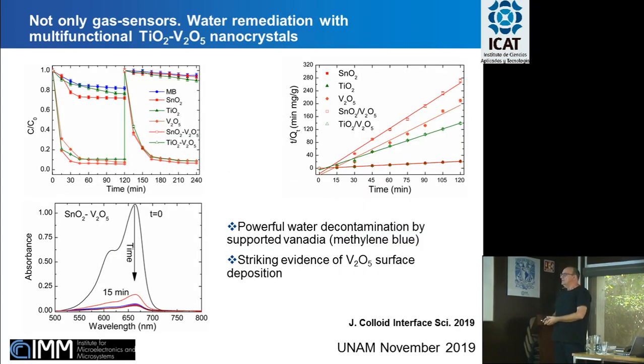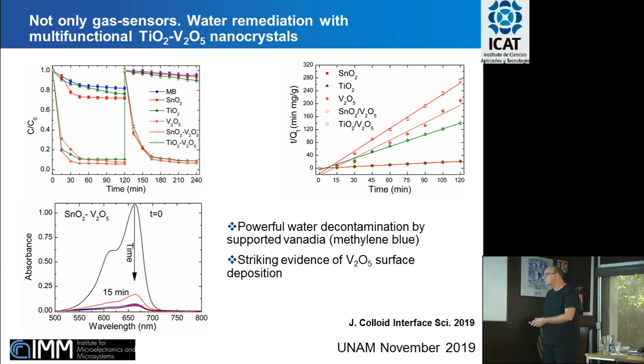And some results about water remediation with these multifunctional titanium oxide vanadium oxide nanocrystals and tin oxide vanadium oxide nanocrystals. We can also prepare other compositions, of course. And we can easily see that there is a powerful water decontamination by supported vanadium with respect to methylene blue. When exposed to methylene blue in the dark, we see that the pure material goes very rapidly to saturation, while the surface modified material can extract up to 80% of the initial methylene blue concentration in just 20 minutes, and after concluding the cycle, they can repeat it once again, while of course the pure materials are completely saturated.